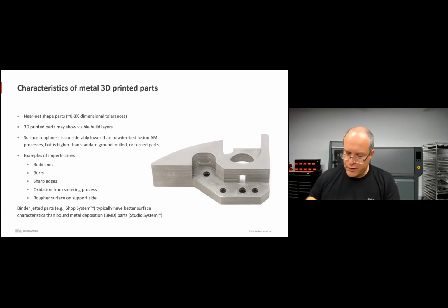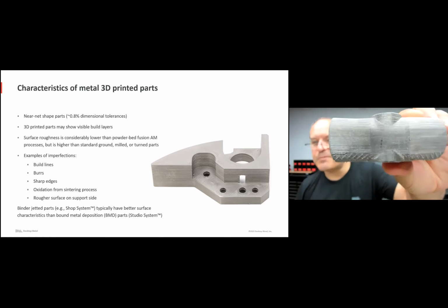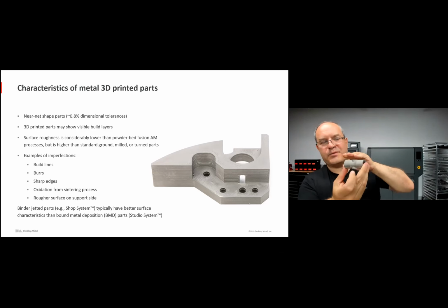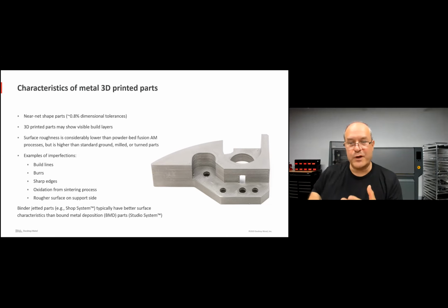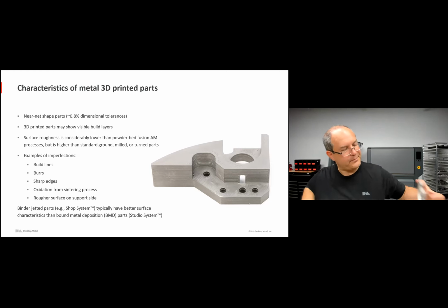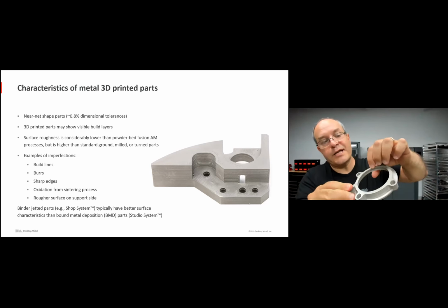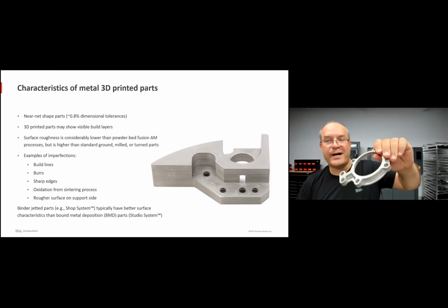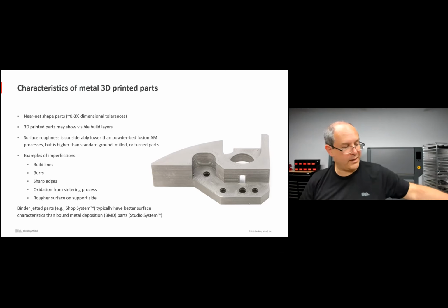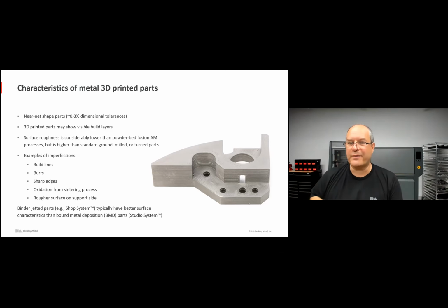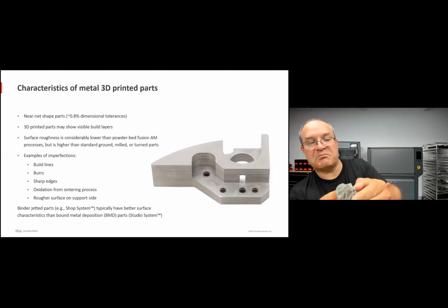And so 3D printed parts do show some visible build lines. So here's a sintered part, and you'll kind of see the layers. This is the printing orientation, prints layer by layer. And so you can see visible layer lines. If you need to get rid of them, a few different options. Surface roughness is considerably lower than powder bed fusion, another common way to produce metal parts, but it is a rougher surface than standard, ground or milled or turned parts. So for example, the surface roughness of this part, it's quite smooth, definitely smooth to the touch, but it'll be probably 3 or 5 micron average roughness, whereas machined parts are going to be smoother, maybe by a factor of 5 or even 10. And there will be, depending on the printing technology, some imperfections. You might see build lines. There might even be, depending on the geometry, some burrs that you may want to get rid of.